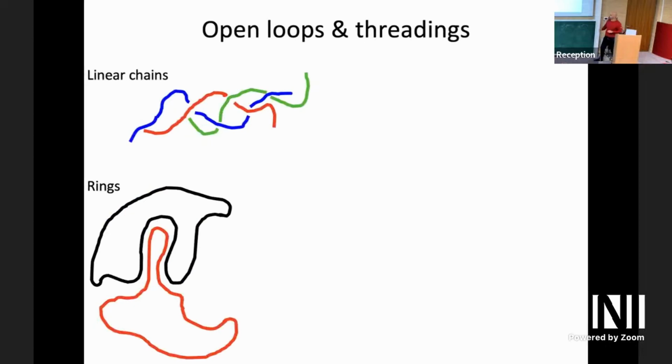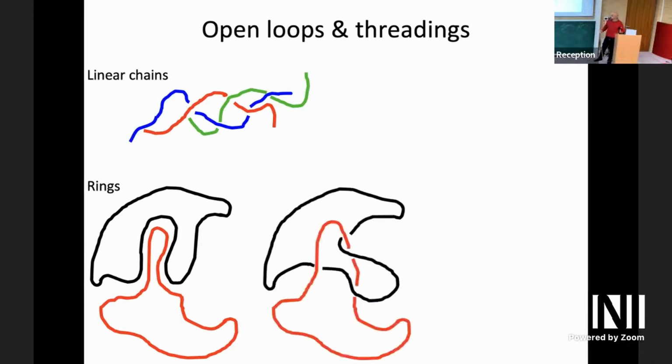So imagine that for linear chains, each chain is protruding into the others and moving, but essentially the topological constraints are non-permanent. They evolve in time, but they are non-permanent. Well, for rings, this unlinkedness is pretty important, and this is permanent by construction, if you want. However, because of the ring topology, nothing prevents you from having some sort of